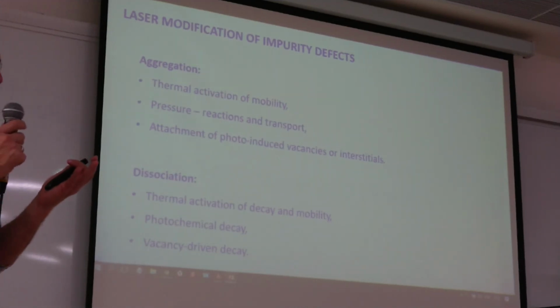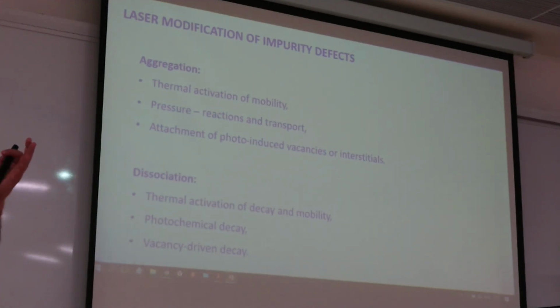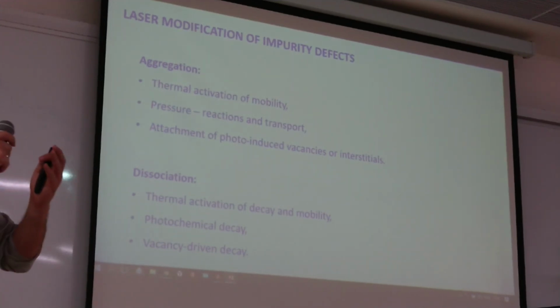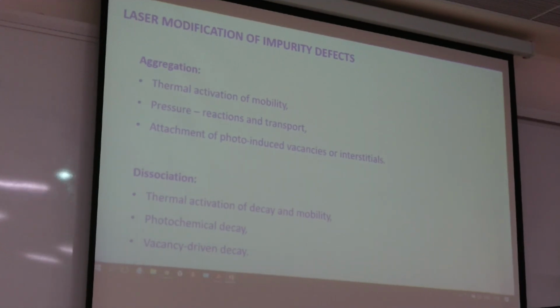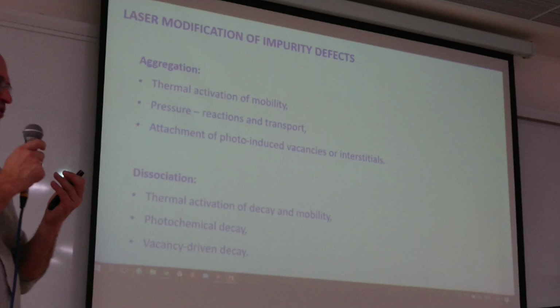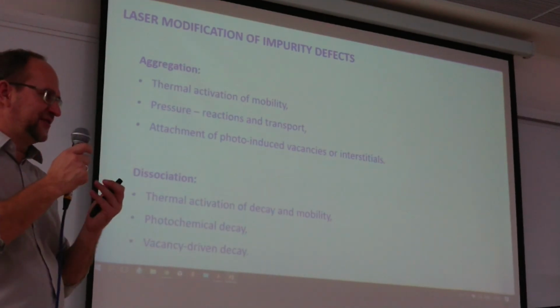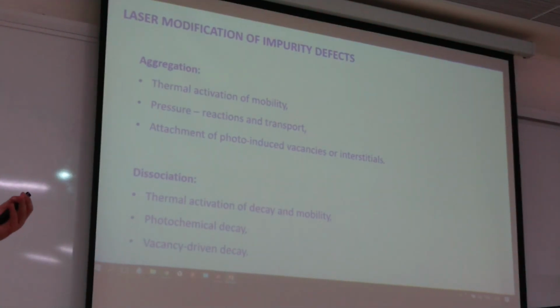Because if we have a vacancy, some kind of stick atoms making the rarefaction, and if we increase pressure, pressure induces more vacancies to come to this region to decrease the local pressure. And on the opposite, if we have an interstitial, which pushes the atoms in the lattice away, high pressure is not favorable for interstitials, and external pressure makes the interstitial leave this region. So the pressure gives not only reaction but also transport of defects.